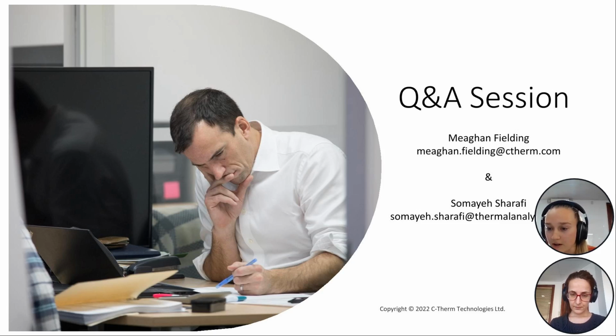I think there were a couple more above. I need to test my samples under argon. Is that possible with the DSC and STA? Yes, it is. Our DSC is equipped with inert gases, argon and nitrogen, and we can also use it in air, and switch between the different atmospheres, from inert gas to air. In our last webinar, you can see the good results we got from rubbers, where we switched from nitrogen to an air atmosphere in order to determine the amount of carbon from the DSC data. As Somayeh mentioned, there was a great application in our last rubber webinar, so I refer you to go and see our labs webinars.